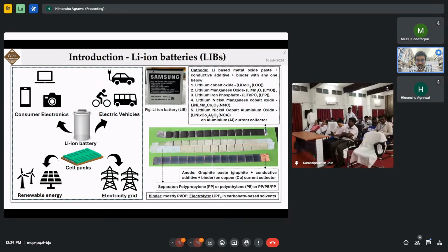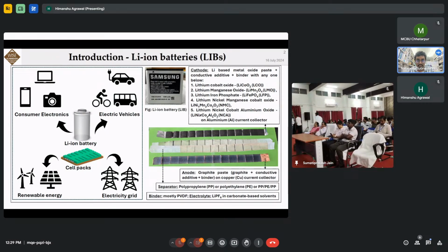The anode is graphite-based on a copper current collector. Similarly to the cathode material, the graphite-based anode is pasted on the copper current collector. The separator is polypropylene, polyethylene, or a combination of polypropylene, polyethylene, and polypropylene. The binder is mostly PVDF, and the electrolyte is lithium hexafluorophosphate in carbonate-based solvents.